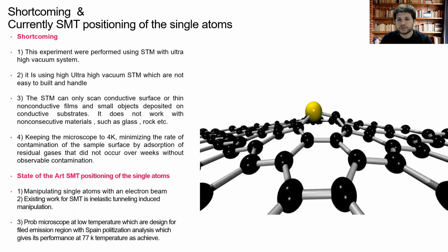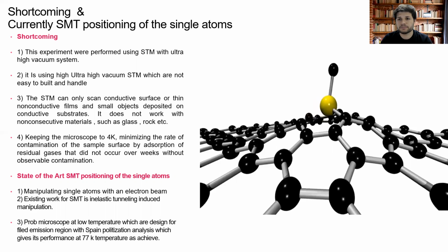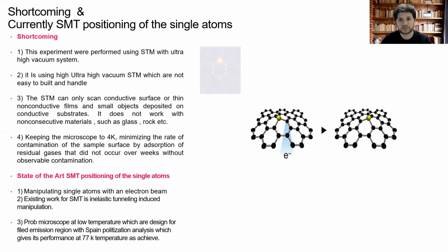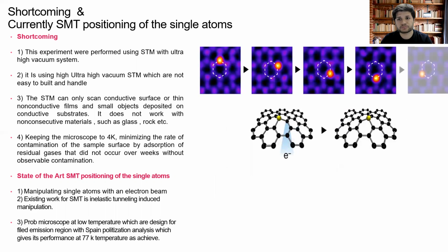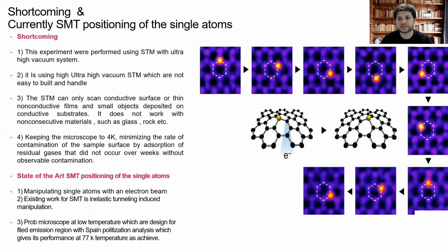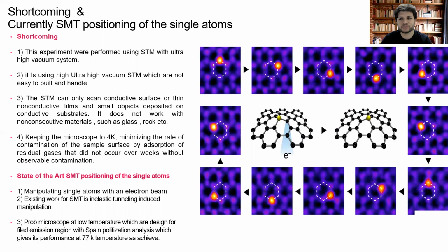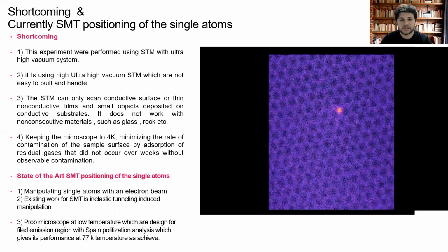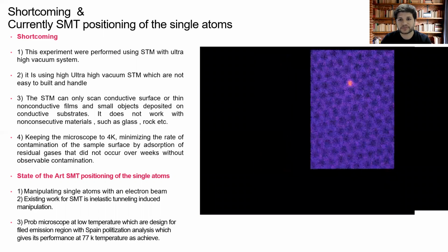In this video, an electron beam focused on carbon atoms next to a silicon impurity atom can controllably make it jump to where the beam was placed. Step by step, this allows silicon to move with atomic precision along external paths. And here is the atom moving from one place to another.